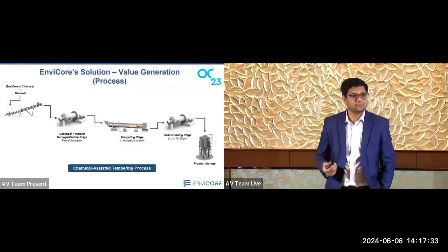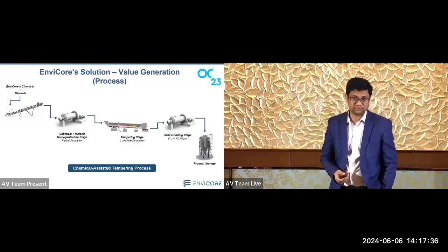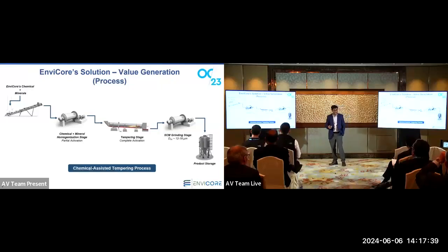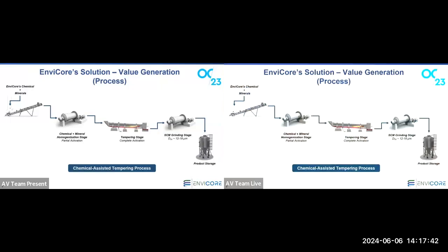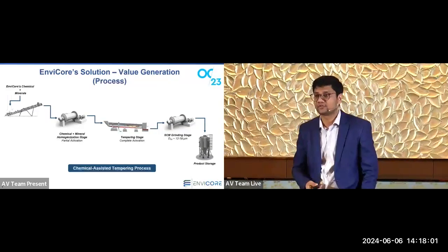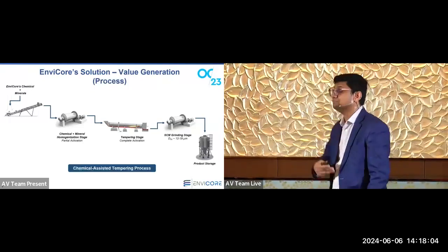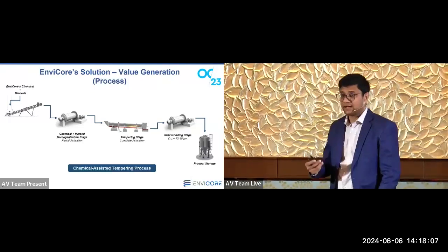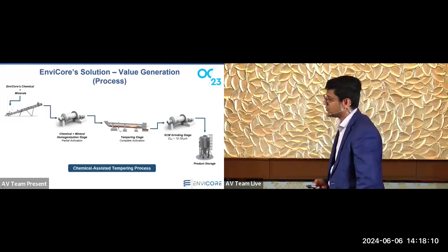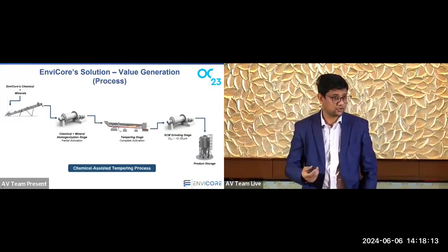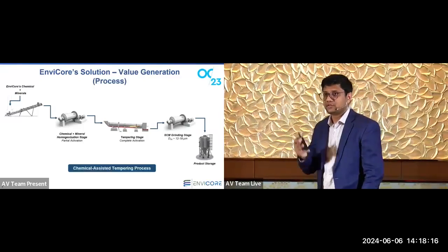So we have developed a patent-pending process that takes any type of mineral feedstock; depending on the favorable mineralogy, it would be ideal. But we have tested recycled concrete fines, aggregates, mining tailings coming from copper, nickel, cobalt, even gold and aluminum mining operations. And then any other type of metallurgical slags, such as steel slag, electric arc furnace, basic oxygen furnace, or even copper slag, coming from completely different operations. And then ash-based materials, ponded ash, bottom ash, and other natural materials, such as clays and natural pozzolans as well.